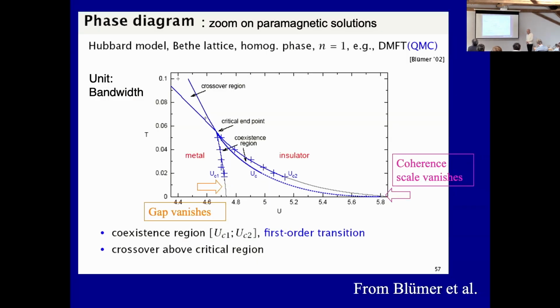So actually, if you zoom in, now this is an actual solution of the DMFT equations on this low energy region, you would have a spinodal of the insulating state when you come from strong coupling, a spinodal of the metallic state when you come from weak coupling, and in between a transition line obtained by matching the two free energies. And please observe that the temperature here, which is basically expressed in units of the bandwidth, is almost 2 orders of magnitude smaller than the bare energy scales of the problem, which is another hallmark of strong correlation phenomena: the energy scales that are relevant at low energy are way, way smaller than the bare energy scales, which is what makes the problem difficult.